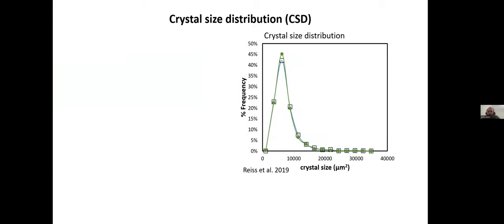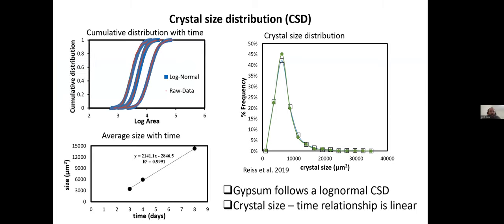I also, from the software, deduced the size distribution of the crystals. You see here a duplicate of an experiment just to see that I reproduce myself. And what we get is a log normal size distribution. There are very few very large crystals. If we look at the graph on the left, this is a cumulative distribution of the size distribution over time from the same brine. So we see that the log normal distribution keeps its shape over time. However, we get an increase of the size of the average crystal. On the bottom is the average size of these three same experiments. And what we see is that we have a linear crystal size time relationship.